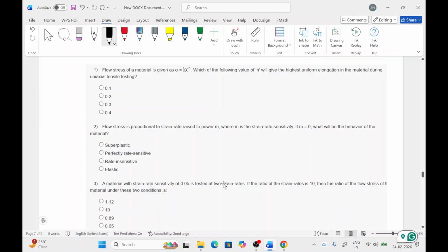So these questions are from the recent assignment. We have asked that the flow stress of a material is given by sigma equals k epsilon raised to power n. Which of the following values of n will give the highest uniform elongation in the material during uniaxial tensile testing? When you study in the professor's videos, one term comes when we differentiate this equation with respect to epsilon, so d sigma by d epsilon will give k epsilon power n minus 1 into n.